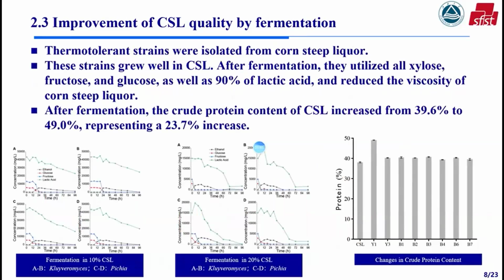Although Aspergillus niger can decrease mycotoxins, its ability to enhance protein content is limited. We also found that several yeast strains can grow in CSL and utilize various small molecule compounds, including lactate. Among them, Kluyveromyces marxianus can decrease over 90% of lactate after fermentation. With Kluyveromyces marxianus, the crude protein content of CSL increased to 49%, a 23.7% rise, showing higher protein-enhancing ability than Aspergillus niger, and thus enhancing the value of CSL.